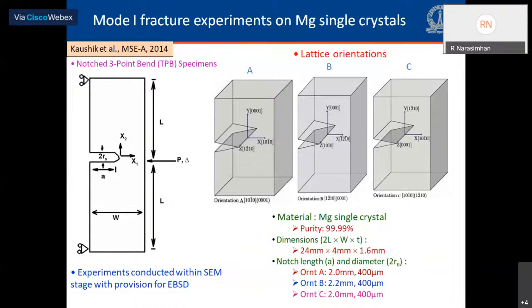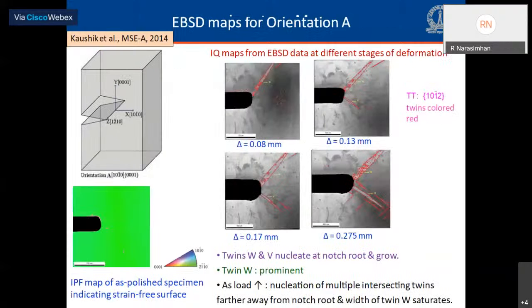The dimensions of the specimen are listed at the bottom. The width of the specimen is about 4 mm, the span about 24 mm, thickness around 1.6 mm. And the notches in these specimens were cut using electric discharge machining, EDM, to a diameter of about 400 microns. The crack length to width ratio, a by W, is about 0.5. These are electron backscatter diffraction maps, EBSD maps, corresponding to orientation A, which I have shown at the bottom left side. Now remember, in orientation A, the C-axis is along the normal to the flat surface of the notch, as you can see in the schematic on the left side top.